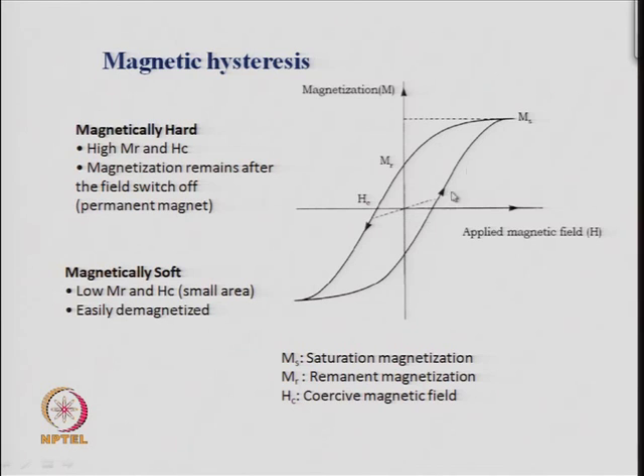Now, ideally in a normal ferromagnet, you will see this kind of a hysteresis loop. As you change the magnetic field, it increases, reaches a maximum, then you decrease the magnetic field, the magnetization will start decreasing. However, it will not come to 0 from where you started, but will intercept the y axis at some position. And this point where the magnetization cuts the y axis is called the remanent magnetization. Now, the field applied at this point is 0. So, you have a net magnetization which remains even in the absence of a magnetic field, and hence it is called a remanent magnetization, and this is a property of anything which is ferromagnetic or ferrimagnetic, and it is because of the magnetic domains present in the magnetic material and the alignment of the magnetic vectors within those domains.